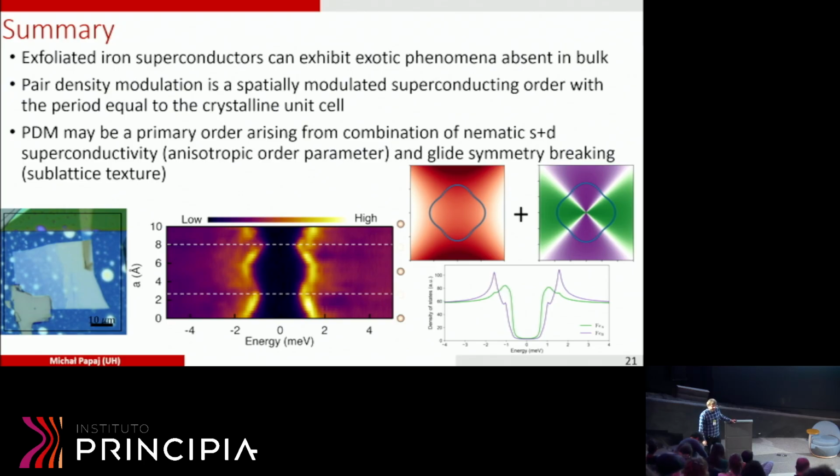And you have those two domains. Now, there's a strong peak associated with this pi that's on the iron sublattice that shows up, and you saw it goes away at 9 Kelvin or so. But if there was a small modulation with different domains, you could still see it in the Fourier transform of the actual selenium atoms by comparing a Qx and Qy peak.